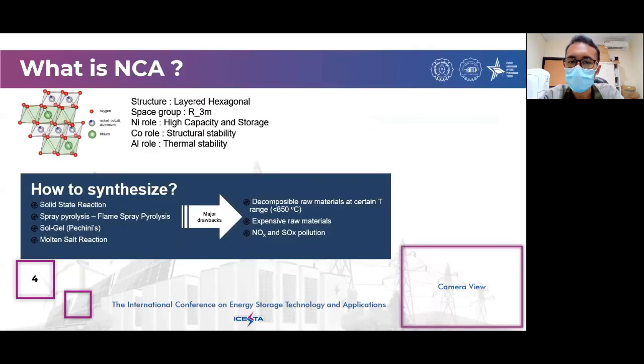Lithium nickel cobalt aluminum oxide, or NCA, is considered one of the most promising cathode materials for lithium-ion batteries, owing to its excellent properties such as high Coulombic capacity, energy, and power density. Currently, NCA with high nickel content is preferable because nickel is less toxic and not as costly as cobalt. In addition, the nickel-rich cathode material has a higher capacity than high-cobalt LCO.